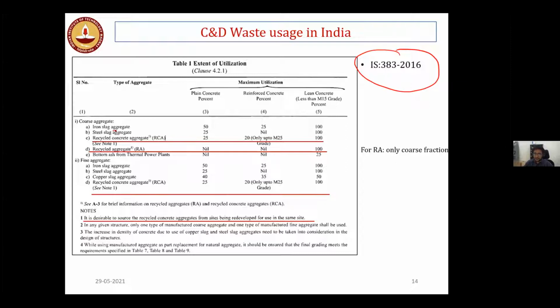It says that we can use the recycled concrete aggregate up to a percentage of 25% if you're going with the plain concrete. If you intend to use the recycled aggregate for reinforced concrete, you can use up to 20%. But because it's a reinforced concrete, there could be some durability or corrosion related issues. So they restrict it to the application up to M25 grade of the concrete.